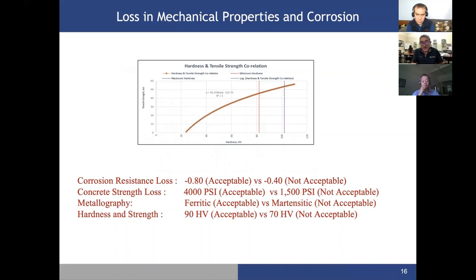Give you an example of what's happening after a tower that is exposed partially to wildfire. The corrosion potential of minus 0.8 volts versus copper sulfate indicates it's acceptable. However, when you do the measurements and you get minus 0.40 versus copper sulfate, it is not acceptable. It means there is no zinc on that surface that can protect this structure.